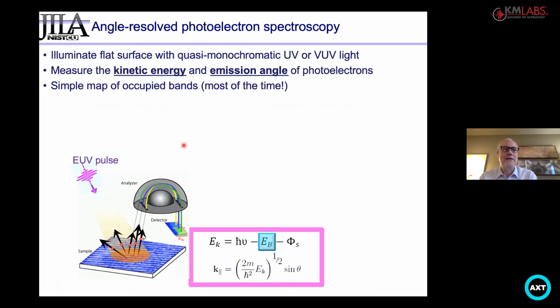In angle resolved photoemission, what you do is you illuminate a flat surface with quasi-monochromatic light, generally in the ultraviolet or vacuum ultraviolet region of the spectrum. So you want to be above the work function of the material, and you want a very flat surface, which generally means a single crystal surface.